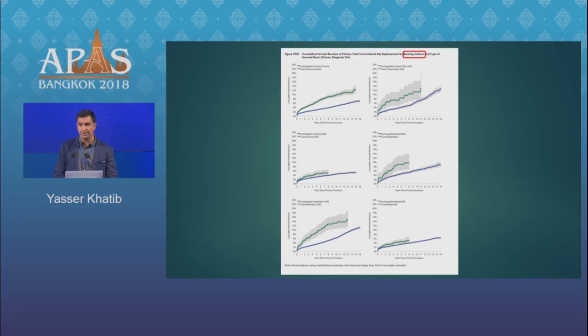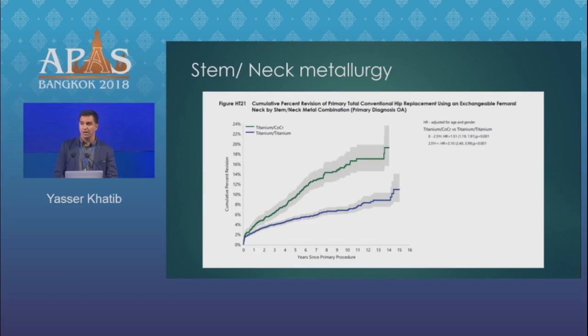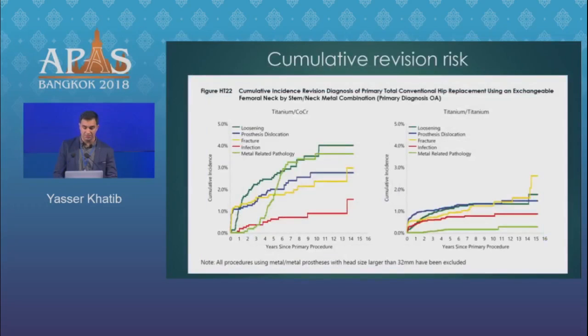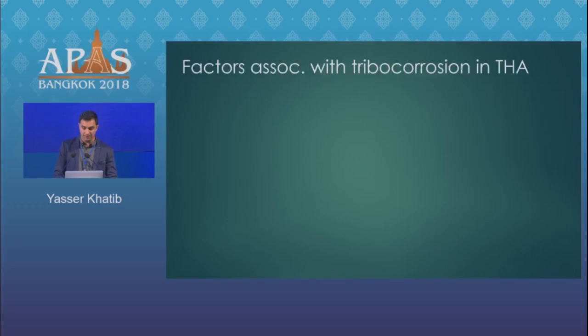So in green here we have the exchangeable necks, and in blue is the fixed necks, and we can see that it's always higher. And a component of this early failure rate is because of the earlier corrosion. And it also has to do with metallurgy. So a lot of these components have a chrome cobalt component with a titanium neck, and then we can see that the different metals lead to increased corrosion and increased failure compared to a titanium construct. And that same relationship applies regardless of what the mode of failure is.